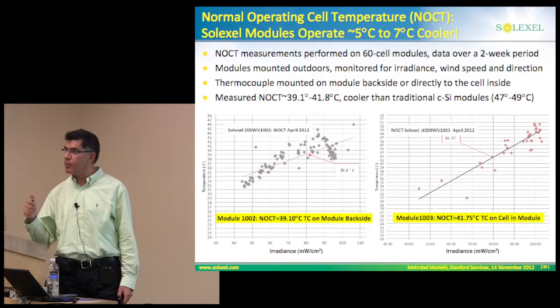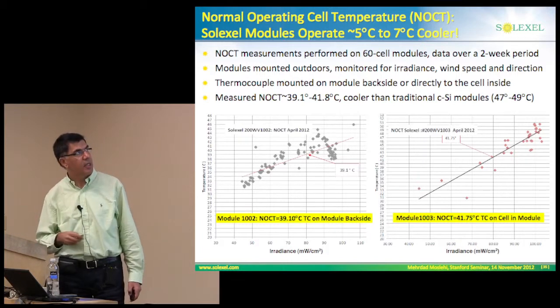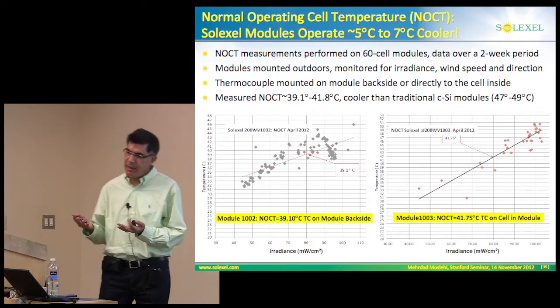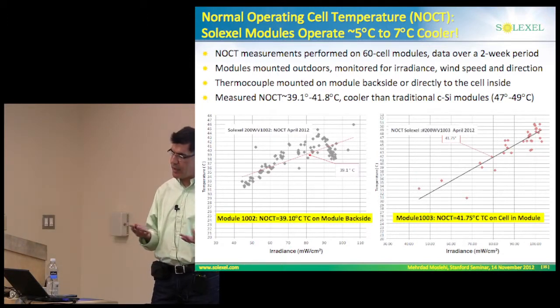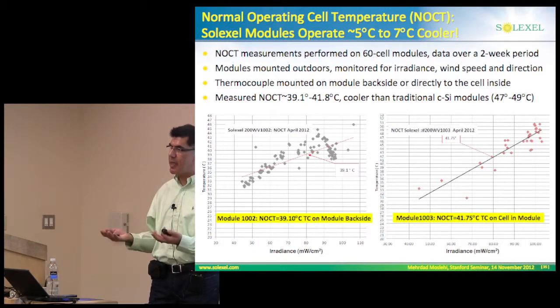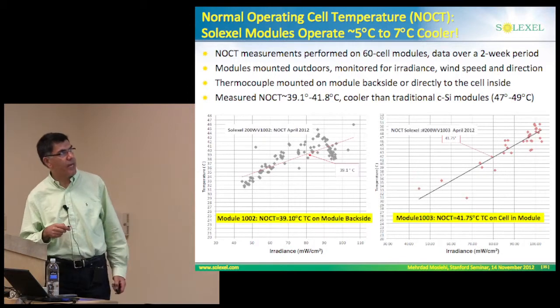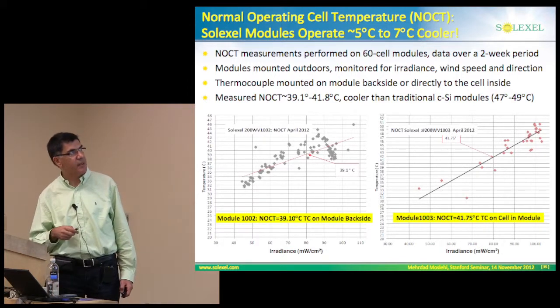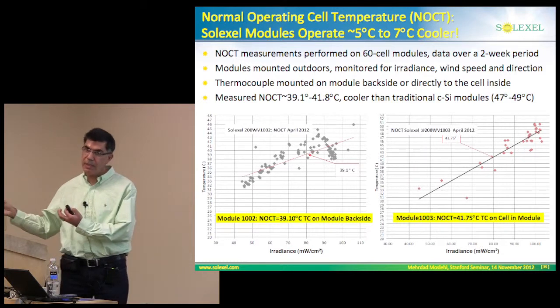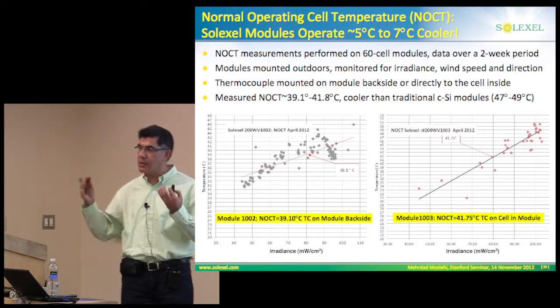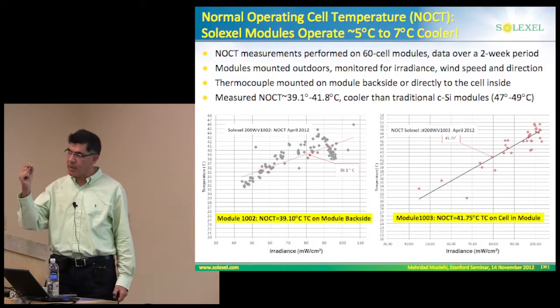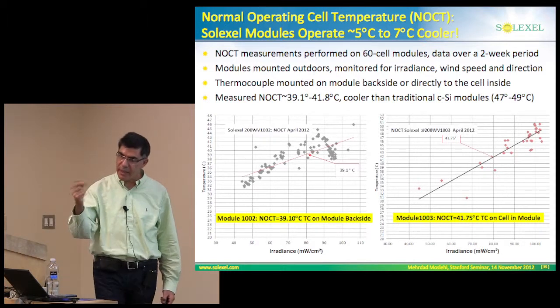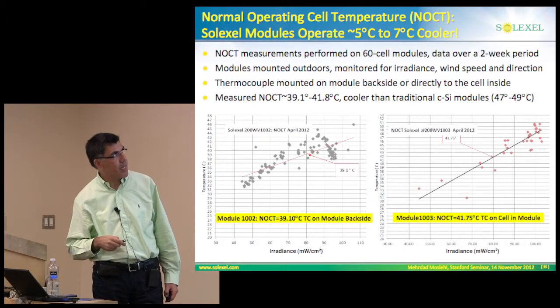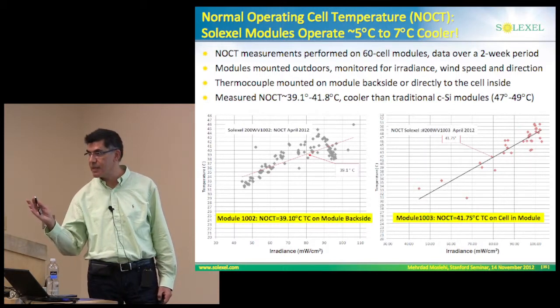As I mentioned, another important parameter is normal operating cell temperature. If you have a technology module that operates at lower temperature in the field, obviously that's better in terms of energy yield. So we have done measurements in the field on our full-scale 60-cell panels over a 2-week period, compared side by side with standard crystalline silicon panels. In this case, thermocouples were attached on the cell inside the panel and also behind the panel. Basically, the NOCT for our cells is about 5 to 7 degrees cooler than the reference crystalline silicon panels.